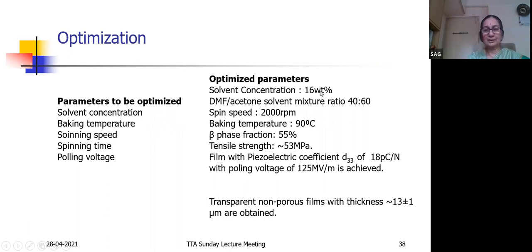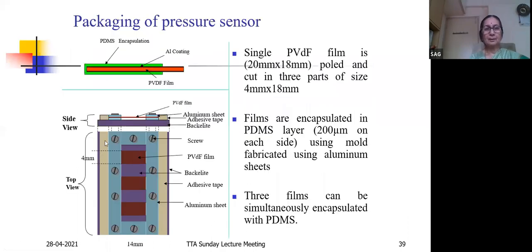Solvent concentration was 16wt%. These are optimized parameters, and this gave us transparent non-porous films of around 13 micron. Then we packaged it. This is an aluminum coating on both sides of the film. Then we used a packaging. This is a cross section of the package. The single PVDF film of around 20 millimeter by 18 millimeter was poled and cut into 3 parts of 4 mm by 18 mm.